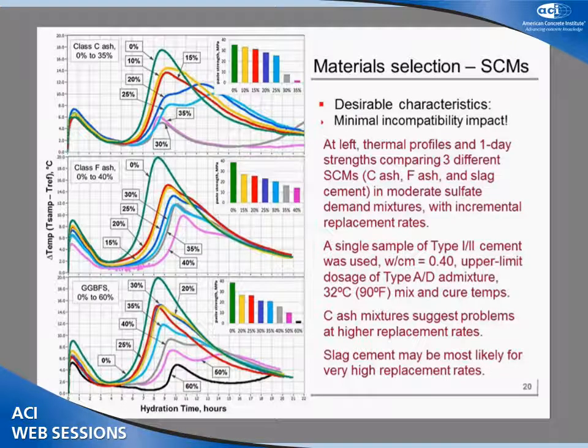Now, in the choice, the selection of, and the tolerance for the level of replacement rate of the particular SCM materials, this is an ideal type of test to get a really good feel for what the performance trends of these materials is going to be and where the sensitivity might be for maximum practical level of replacement rate given your other materials and proportions. Here we've taken 3 different representative SCMs, a slag cement, a Class C fly ash, and a Class F fly ash, and compared them at various replacement rates in these paste mixtures in the laboratory. Very simple process. All these were done in virtually a couple of hours.